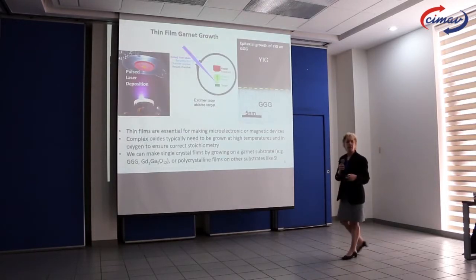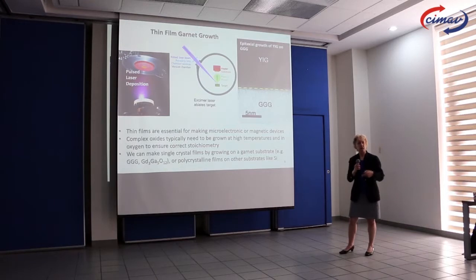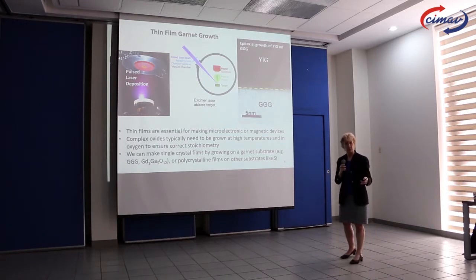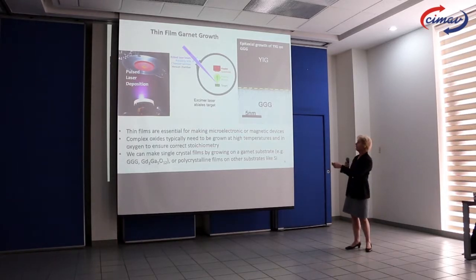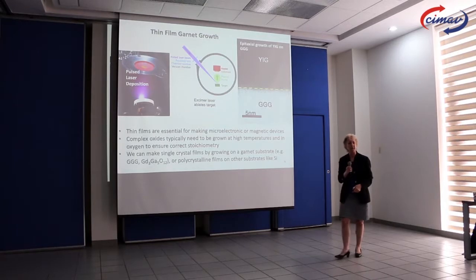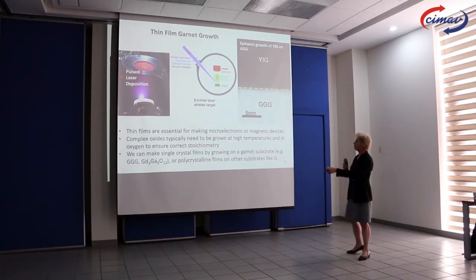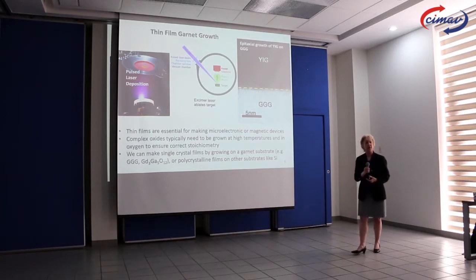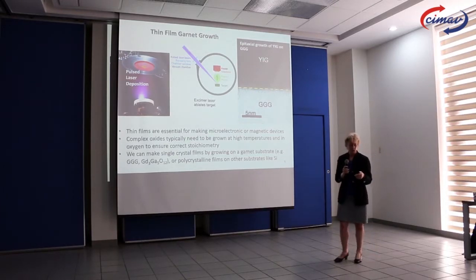Okay, now, we grow thin films in my lab. I know some of you grow thin films by sputtering. We grow thin films by pulsed laser deposition, where we have a laser beam that hits a target. A plume of material is evaporated from the target, and that hits the substrate, which is usually heated up to quite high temperatures. So this is what it looks like. You can see the plume of material coming off the target, and the substrate's up there. And by doing it this way, we can get good quality films.